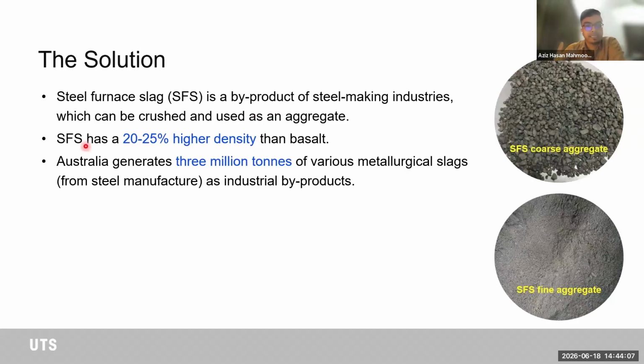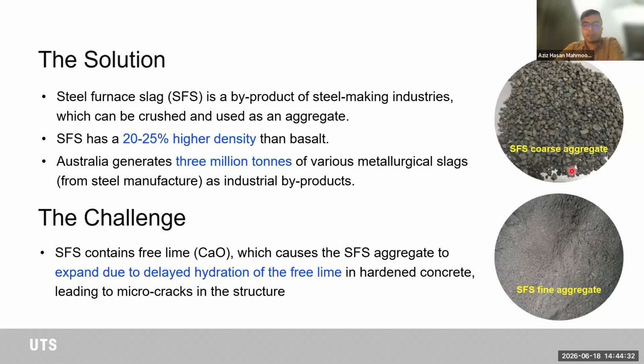Now, steel furnace slag has a 20 to 25% higher density than your typical, naturally available stones. Australia also generates about 3 million tons of various metallurgical slags as an industrial byproduct. So in the concrete, we're trying to incorporate something that we usually perceive as a waste and convert that into a value-added product. But this particular aggregate comes with a challenge. It has free lime, which causes the aggregate to expand when we use it in hardened concrete, and that free lime reacts with water in the concrete, and it causes delayed hydration and forms calcium hydroxide, which is a chemically active material, and it also expands with time.